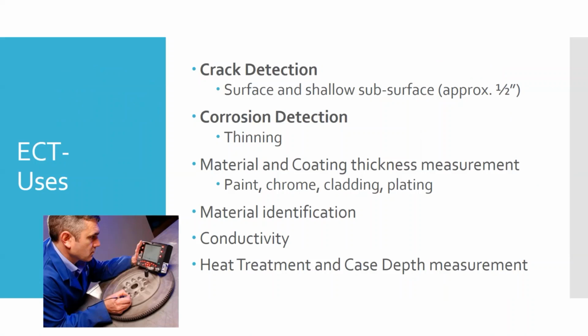A few years ago, Southwest Airlines had a plane with an uncontained fan failure. Unfortunately, one passenger was killed when that chunk of fan blade came up out of the front of the engine, hit a window, and she was pulled through that window in the vacuum. But this eddy current testing is what's used to try to find that before something like that happens. In that case, they'd been doing the proper eddy current tests. The fan blade actually cracked in a location where there was never a directive to inspect that area. And so cracks had formed in an area that was new.